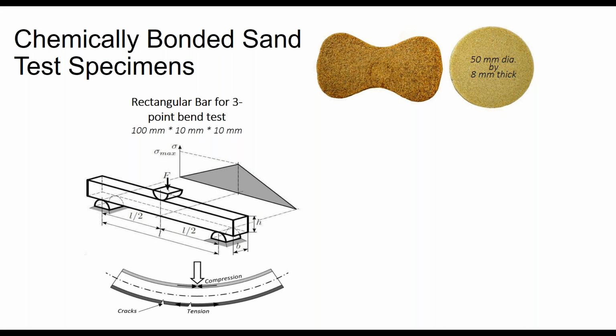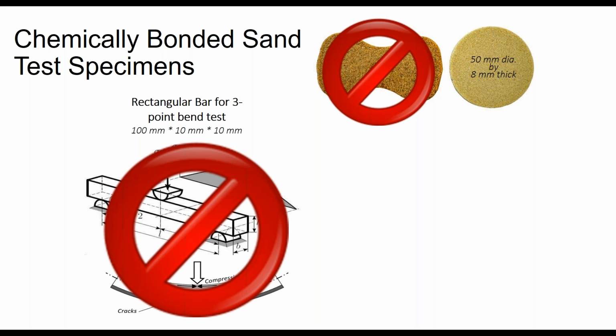On the 3-point rectangular beam specimen, that specimen works well mechanically, but if we try to heat it during test, we can't get any data because the failure mode is premature. But certainly as a mechanical test, the 3-point bend test is excellent for ultimate strength testing, bending moduli, shear, etc. So there are some reasons why we prefer the new alternative standard, the 50mm diameter, 8mm disc. There is no shape factor.